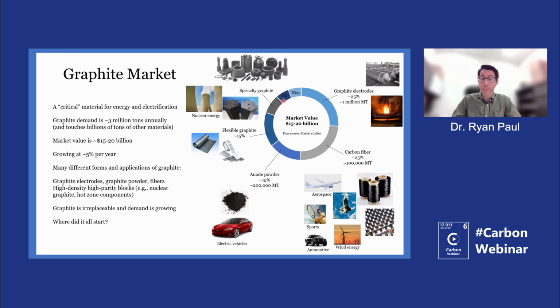So in this particular schematic, I'm highlighting a couple what I think are very important to understand in terms of what graphite really does for technology and society. Starting with graphite electrodes, it's about a million metric tons per year, growing a little bit every year as more and more steel is made through the electric arc furnace process, which is where graphite electrodes are used. They are the electrical conduit to pass high power to melt scrap steel instead of using the traditional blast furnace route. This is about 25% of the total piece.